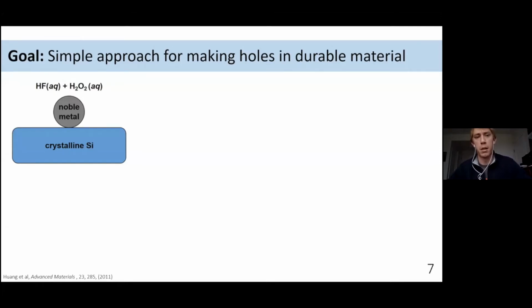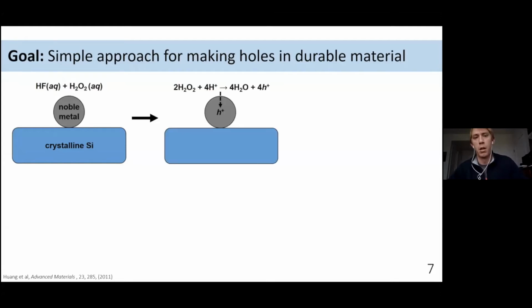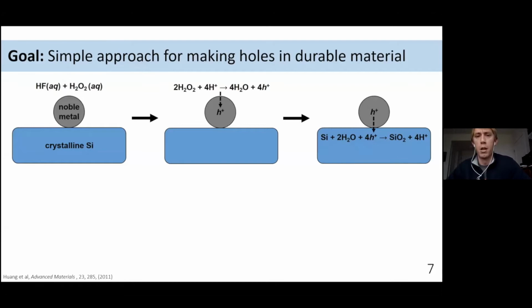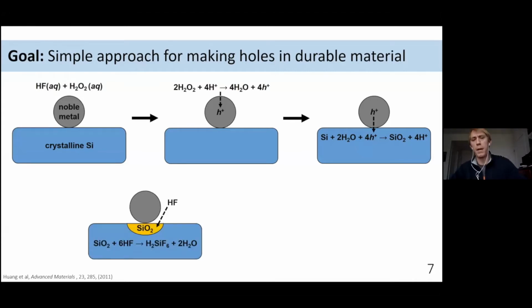And then immerse this in a chemical solution containing hydrofluoric acid and peroxide, which are both pretty common chemicals in the semiconductor space. So the net effect here is that you get a passive electrochemical process where you're reducing the peroxide at the surface of your noble metal. And this then injects a hole into the silicon, thereby oxidizing it very locally at that interface between the metal and the silicon surface. And that oxide is then subsequently almost immediately consumed by the hydrofluoric acid in solution.